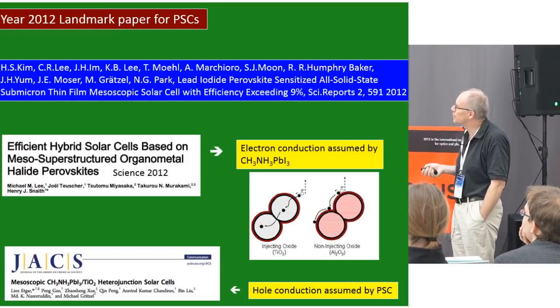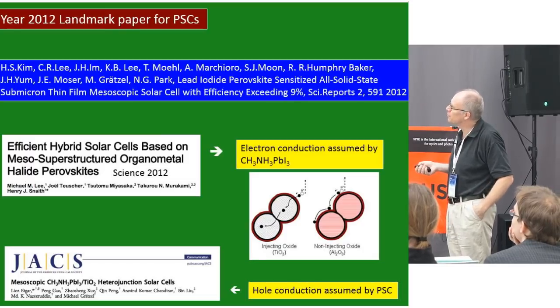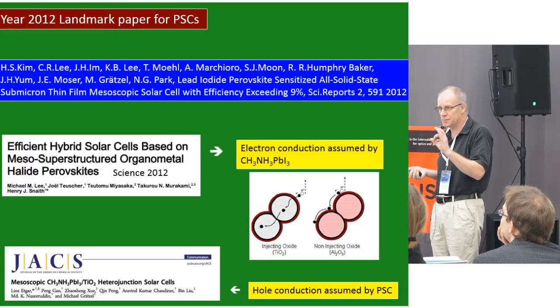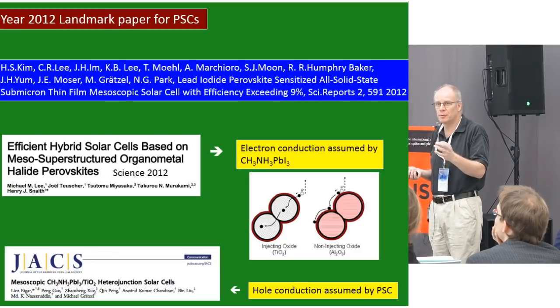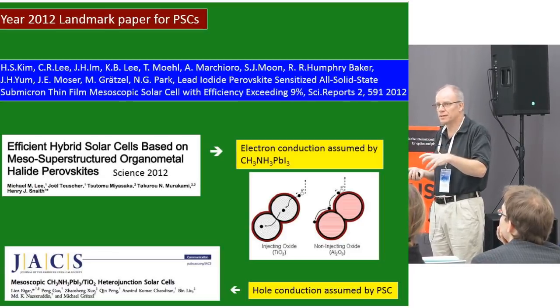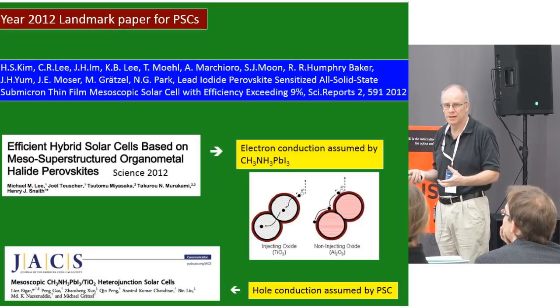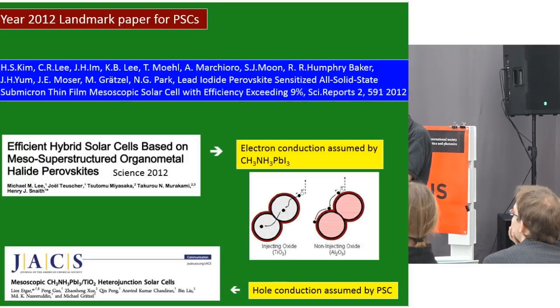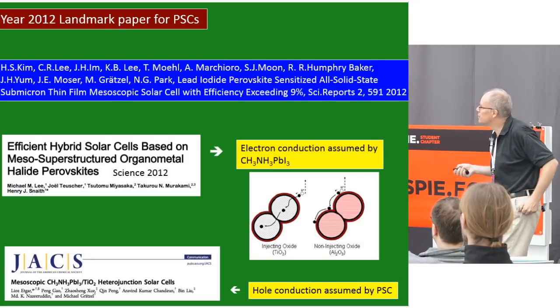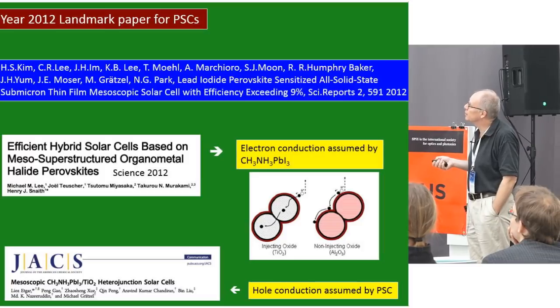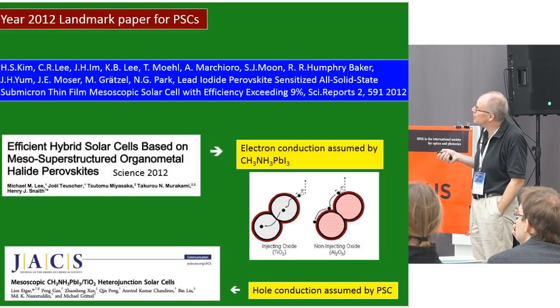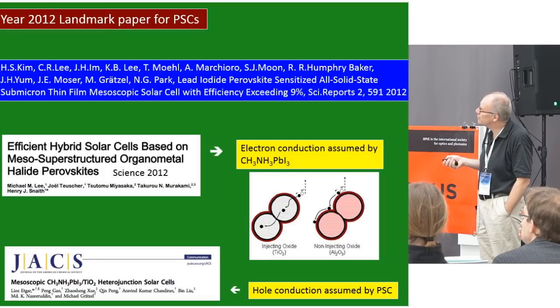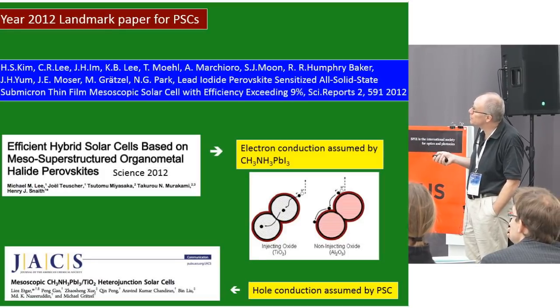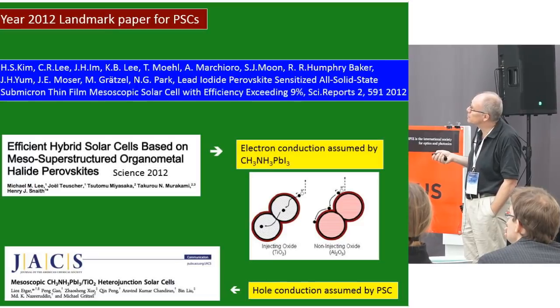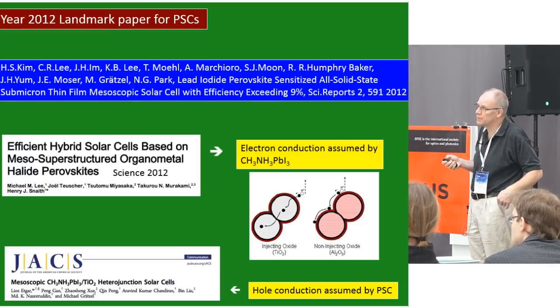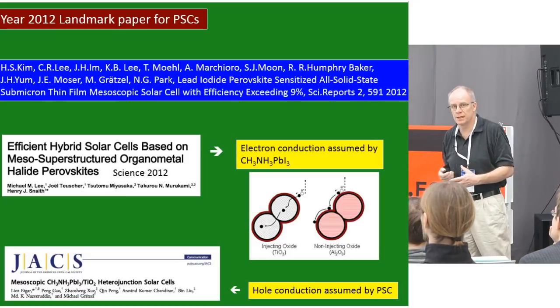Henry Snaith at Oxford had the same idea, but he also came up with the idea that, since the liquid electrolyte was the problem for stability, let's use spiro-MeOTAD, which is a solid hole conductor instead, and see if stability is improved. And that was the breakthrough, to use the perovskite on the TiO2 and then the spiro molecule instead. Then two groups, Nam-Gyu Park together with Michael Grätzel and Henry together with Tsutomu Miyasaka, published independently two papers in 2012 showing that you can use this perovskite material with spiro and get about 10% efficiency and not so bad stability.